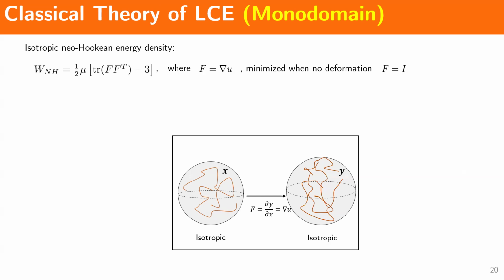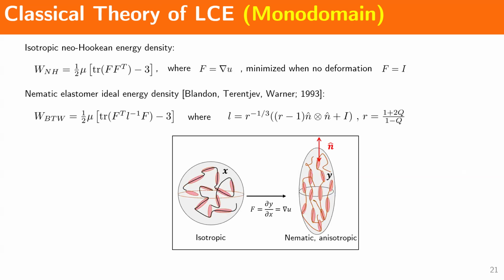So now we also remember, however, that we're cross-linking this material with the nematic mesogens, right? And the nematic mesogens have a preferential direction along this particular direction n. And so these three people, Warner, Terentjev, and Bladon, take into account this anisotropy via this L tensor here, right? So this L tensor basically is the anisotropy tensor that takes into account this preferential direction of the mesogens. Now, this L tensor also encodes all the energy minimizing states.